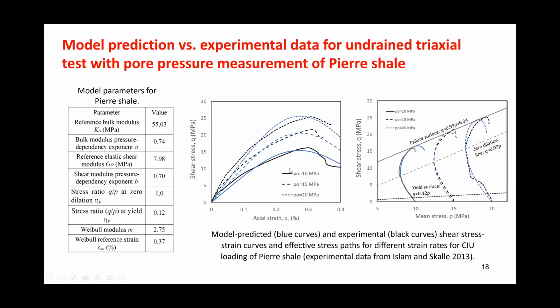You can see that the stress strain curves are well represented for different confining pressures, initial confining pressures, 10 megapascal to 20 megapascal. But more remarkably, you can see the very good fit of the effective stress paths in the PQ plane. Again, all are effective stresses. So it initially shows contraction, hits the zero dilation line or the phase transformation line, then starts to dilate. Then strain softens, so it elbows to the right and down a little bit.